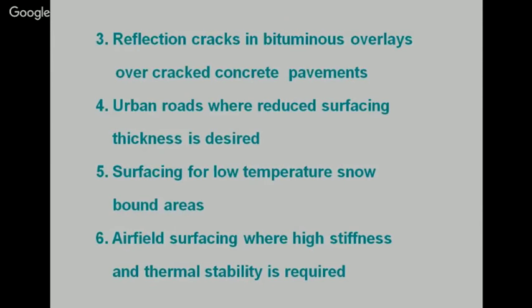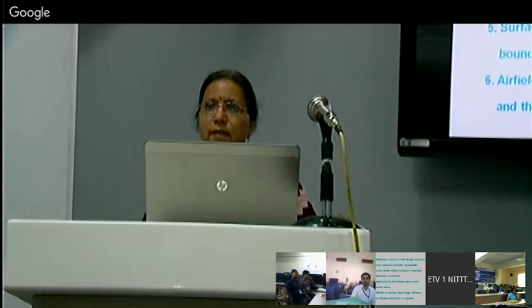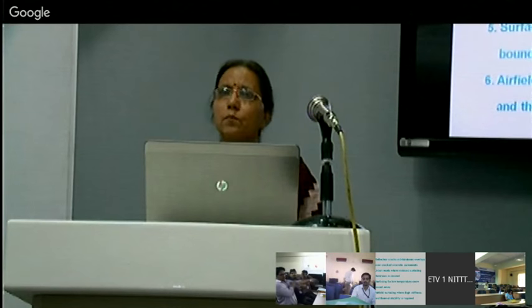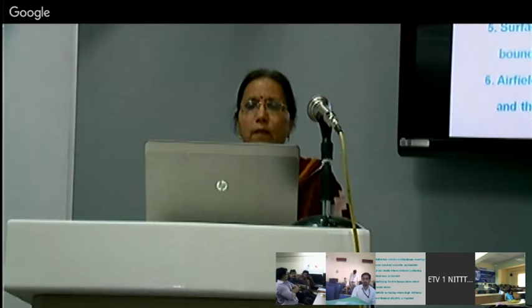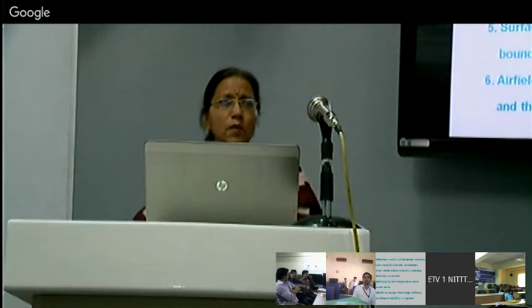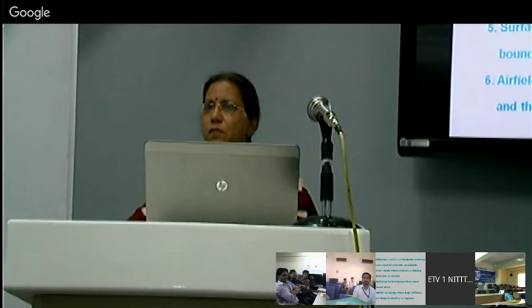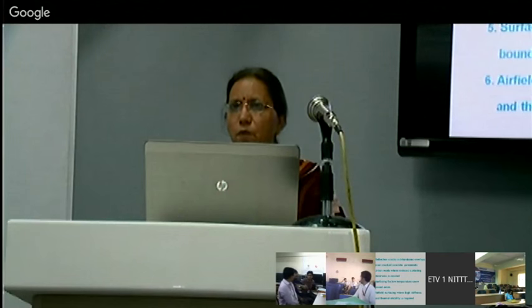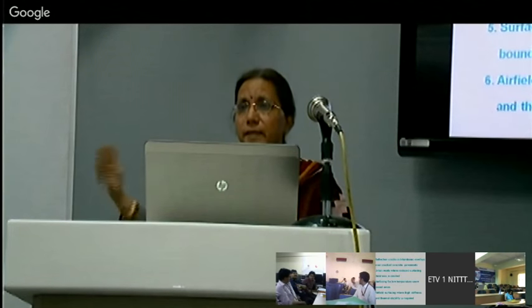Reflection cracking in bituminous overlay over cracked concrete pavement is a major concern. When a cement concrete road cracks, there is no remedy other than giving an overlay of bituminous binders — with modified binder, not conventional binder. For urban roads where reduced surfacing thickness is desired, frequent failure occurs after every monsoon — aggregate chipping goes away and we need overlaying, causing road height to increase every year.